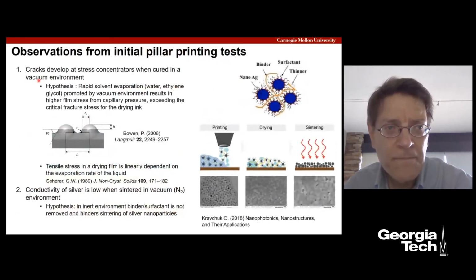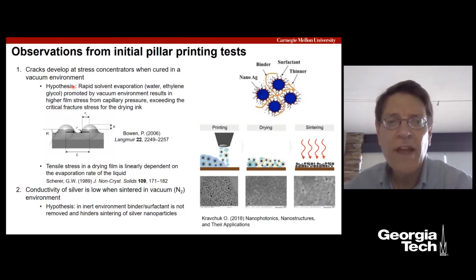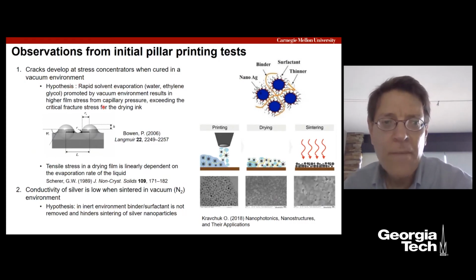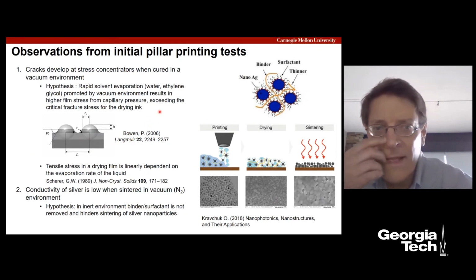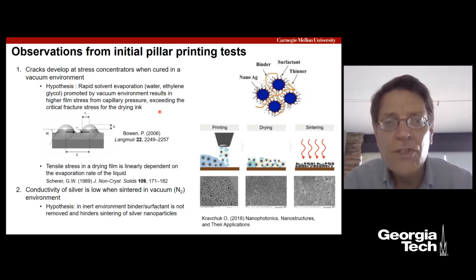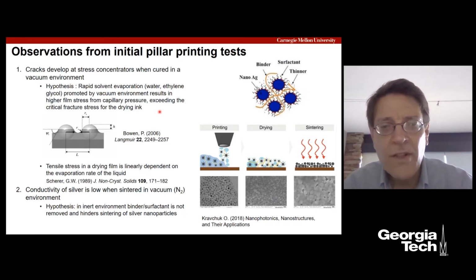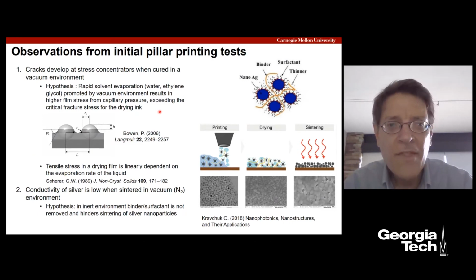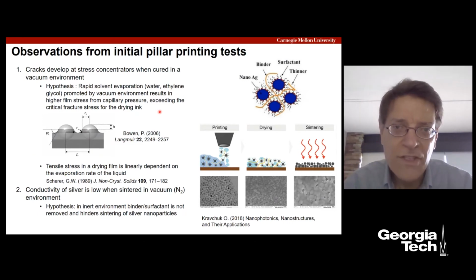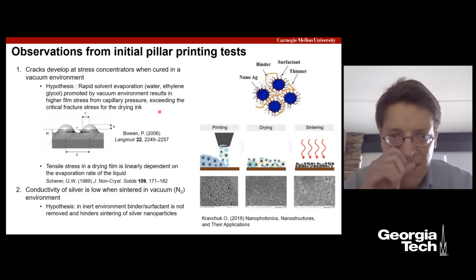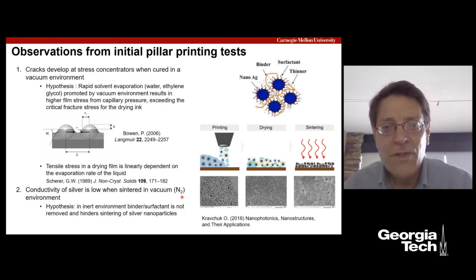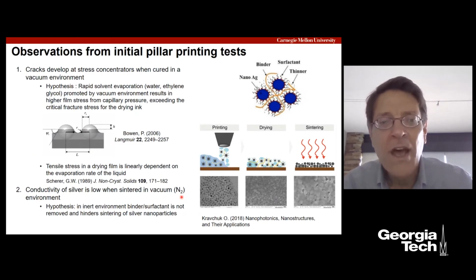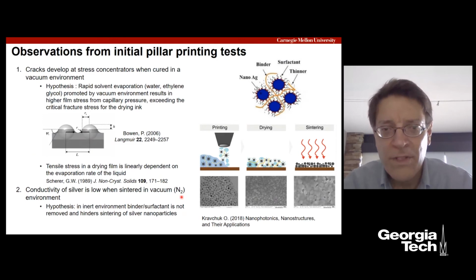A couple of things. One is that when we're curing in a vacuum environment, we were getting rapid solvent evaporation. In the literature, here's one example. It's clear that the tensile stress in the film is going to be directly related to the evaporation rate of the liquid. So evaporating slowly is important, and this is where the drying comes in. Having the drying step, instead of putting this at a high temperature furnace and vacuum immediately, is a critical thing. The second thing we noticed was the issue about the conductivity of the silver: if we were trying to do this in a vacuum environment that doesn't have oxygen, we were getting poor sintering and wondering what's going on there.